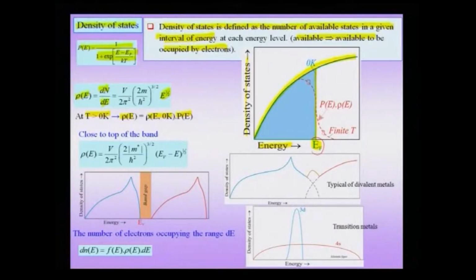Now, there will be electron states which will go vacant here, and there will be electron levels which will be occupied here at higher energy levels. So, this is at a finite Kelvin temperature. In other words, I have taken my density of states at 0 Kelvin and multiplied by the Fermi Dirac function. Now, this kind of a picture is not actually valid when you are close to what you might call the band edge.